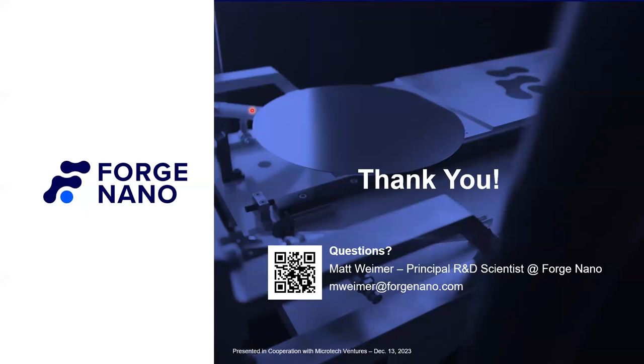As an anti-reflective coating, ALD is extremely successful because you have such great control over those individual thickness layers. You will get the same RI each time you deposit a layer, which is extremely critical for anti-reflection. Films are transparent for this purpose. You can certainly deposit films that don't have any haze, so that isn't a concern. I know we've done some optical anti-reflection coatings, and again, it all comes down to how much of each film